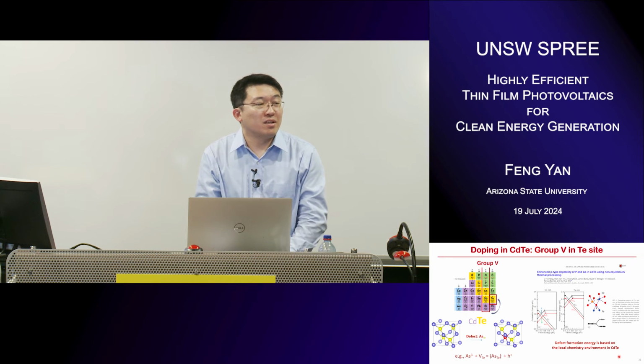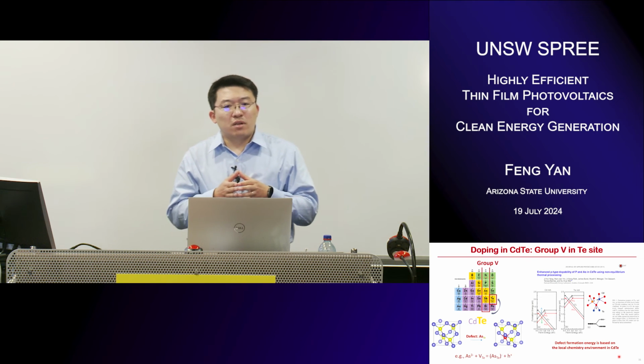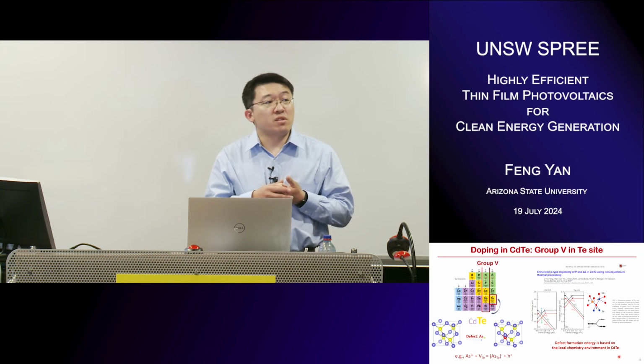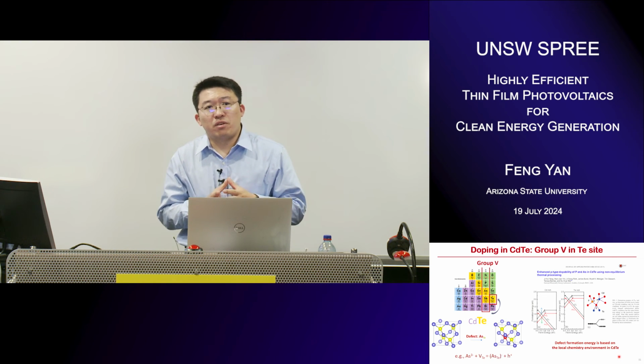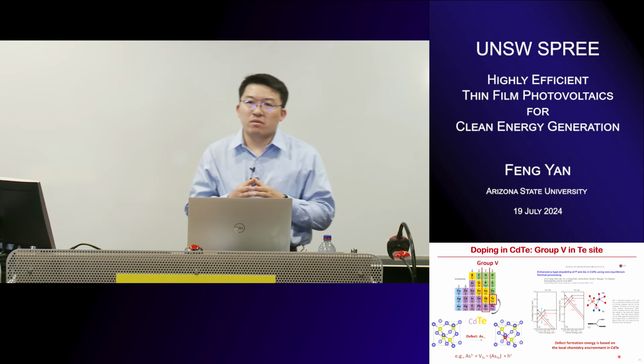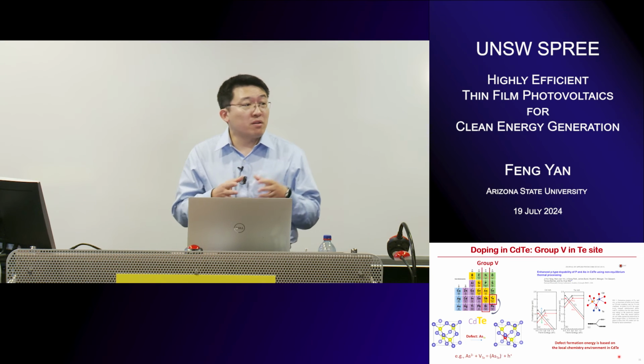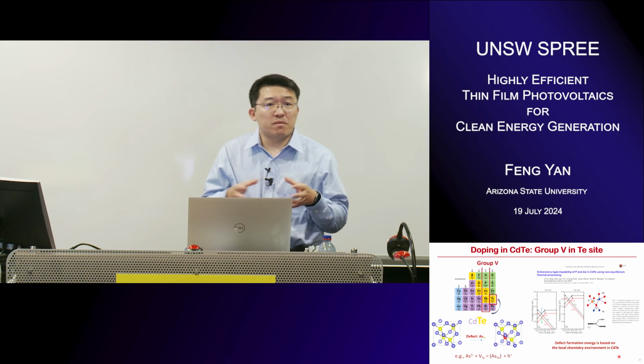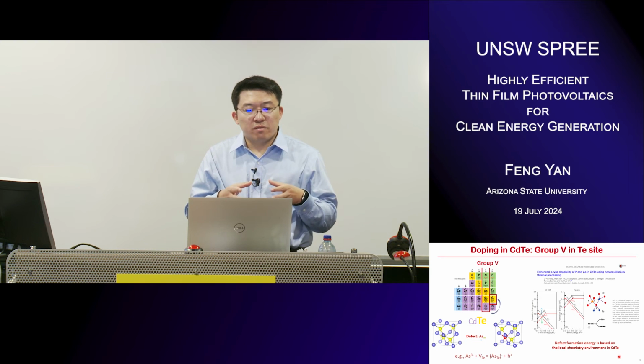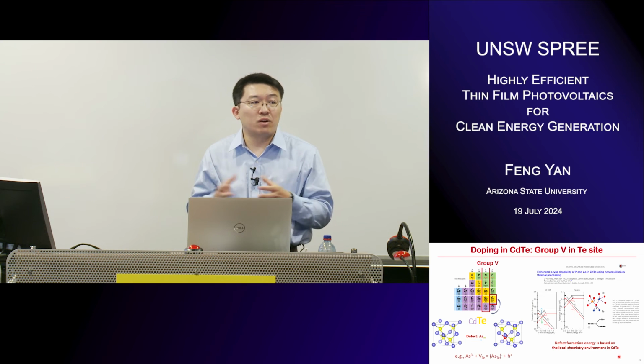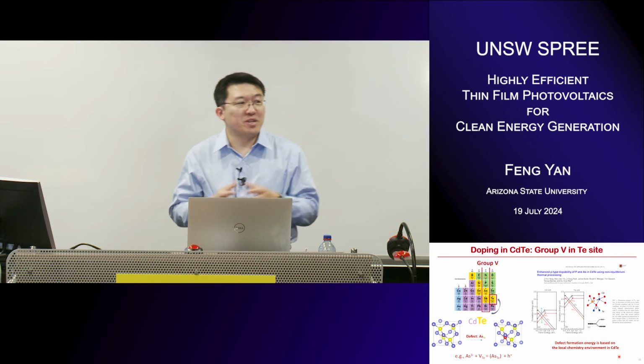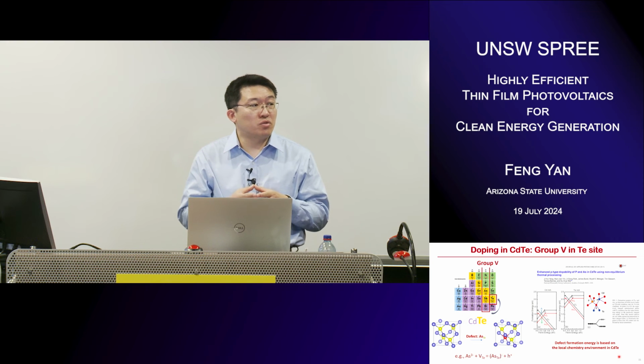A further question. For the cadmium chloride treatment, you don't see the green growth after the... Oh yeah, cadmium chloride has several roles. One of the major roles is grain growth. That's true. The as-deposited film, for example using CSS or VTD, is probably only around 1 micrometer or smaller, but the cadmium chloride treatment will further grow and recrystallize the grains into 2, 3, 5, or even 10 micrometer large grains. So it depends on the treatment condition.